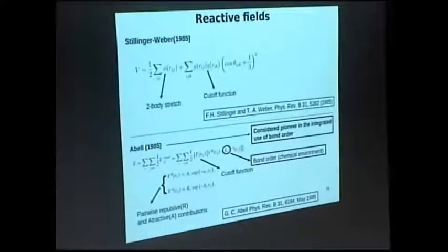The idea is that you have a VR, which is the repulsive part of the potential, and a VA, which is the attractive part of the potential, and the attractive part is controlled by the BIJ. This is the bond order. Then it defines, for example, if you have a carbon, in a few minutes we will see a calculation of the bond order for a carbon-carbon connection.